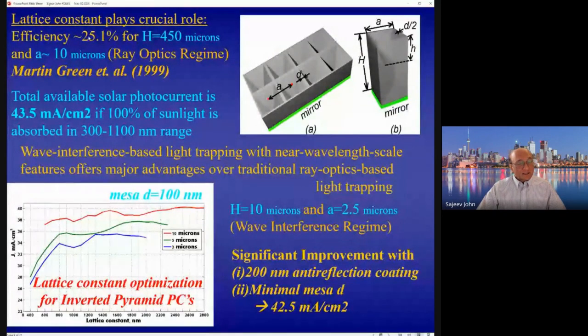That led to the creation of this 25% efficiency solar cell. The thickness of that solar cell was about 450 microns. They were interested in ray trapping effects rather than wave interference. So the lattice spacing between the inverted pyramids in their case was about 10 microns, much larger than the wavelength of light.